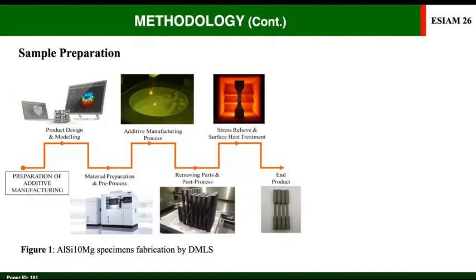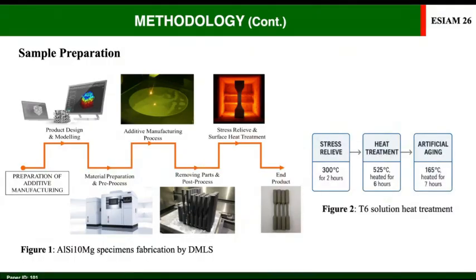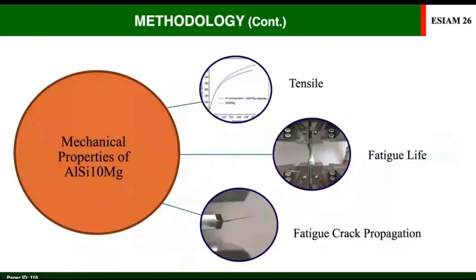In this study, the specimen is fabricated from a CAD input and printed by DMLS. After removal from the chamber, the specimen is further processed by heat treatment: stress relief, solution heat treatment, and artificial aging. Then all as-built and heat-treated specimens were tested by mechanical tests: tensile, fatigue life, and fatigue crack propagation.